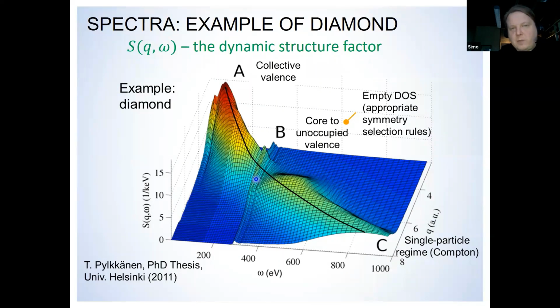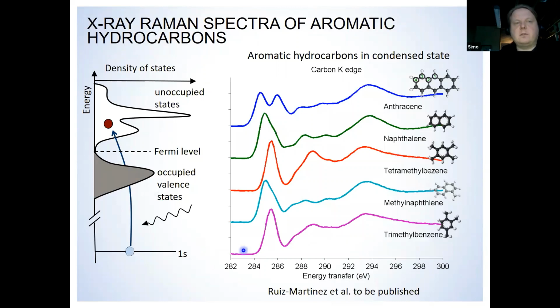So it looks like a minute little detail here, but actually if you zoom in, you can see all the chemical information that is buried there. It's similar to XAS spectra. So these are real X-ray Raman spectra from different aromatic hydrocarbons in condensed states. You can see that all these molecules have different spectral fingerprints, and one can use this for chemical analysis, for example. This would be exactly the same as the XAS spectra, but now done by hard X-ray method.